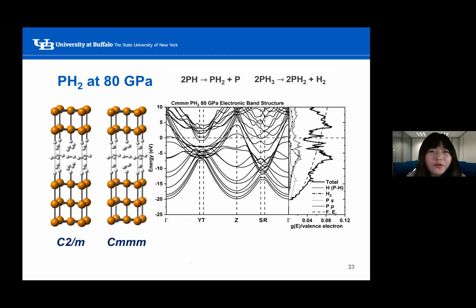So for PH1 to 4 and 6, the structures are all comprised of simple cubic-like phosphorus layers, with the top and bottom layers capped with atomic hydrogens and separated by molecular hydrogen layers. Because the PH2 stoichiometry has the phases with the estimated Tc that's in line with the experiment, and the reactions of PH decomposing into PH2 and phosphorus, and PH3 decomposing into PH2 and hydrogen, are both exothermic, we use the PH2 phases for analysis to represent all of the similar structures.